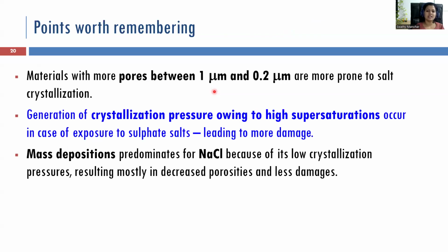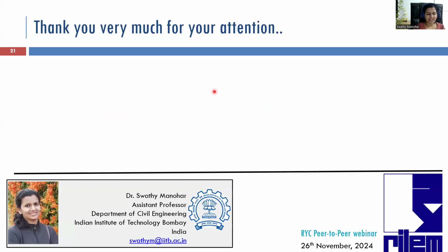Second, in sodium sulfate salt, crystallization pressure would be generated owing to high supersaturation, which could lead to more damage. But with sodium chloride, mass deposition predominates, where the crystals precipitate in the pores, increasing the mass of the system, resulting in decreased porosity and less damage. Thank you very much for your attention.